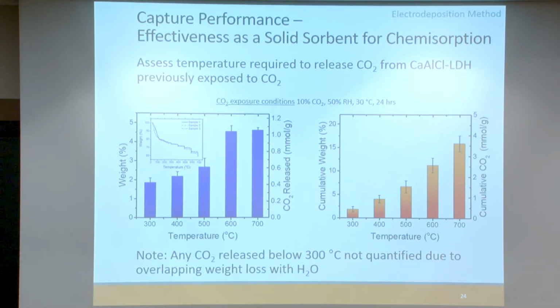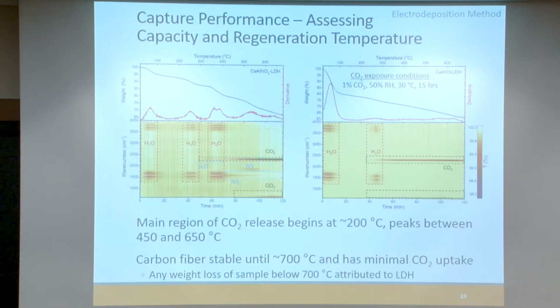Note here that because of the overlapping regions of CO2 and water for both of these layered double hydroxides, we've only looked at what comes off the sample above 300. We still need to quantify how much CO2 is coming off at lower temperatures. Likewise, here 50% relative humidity, so we are still getting chemisorption at this relative humidity. It'll be interesting to look at lower relative humidities and how that changes capacity and regeneration of the material.